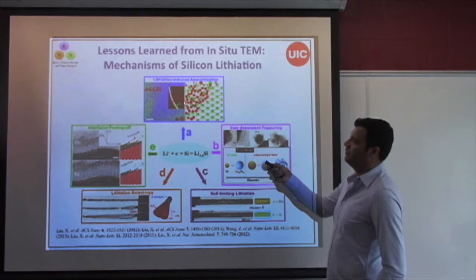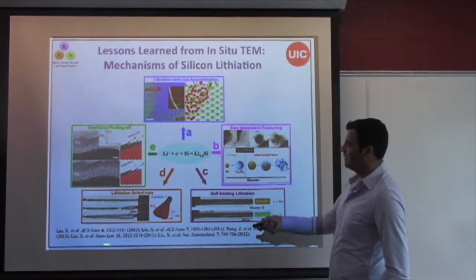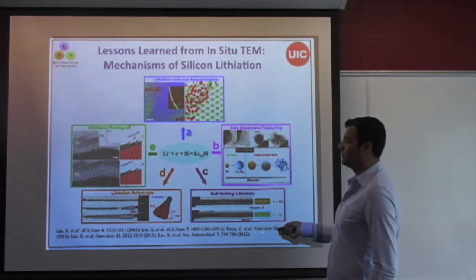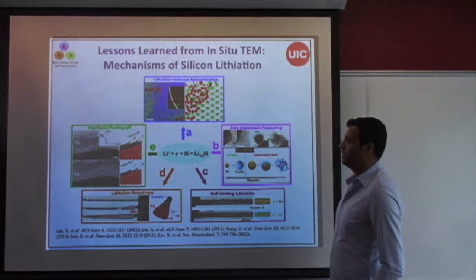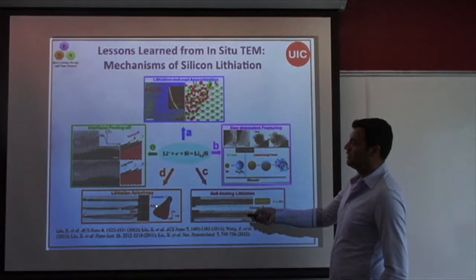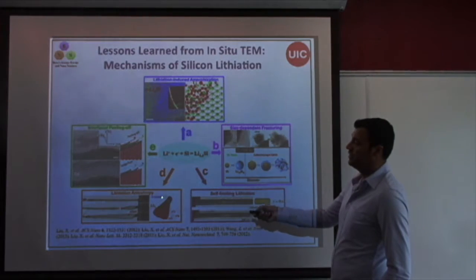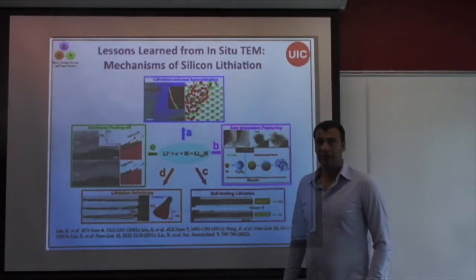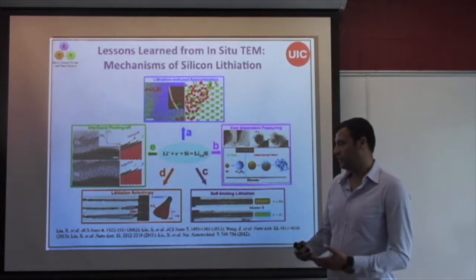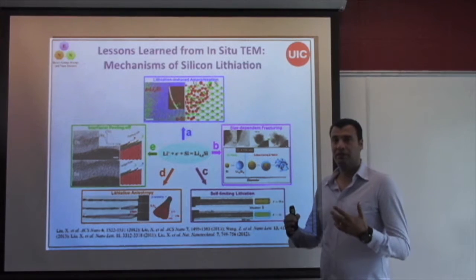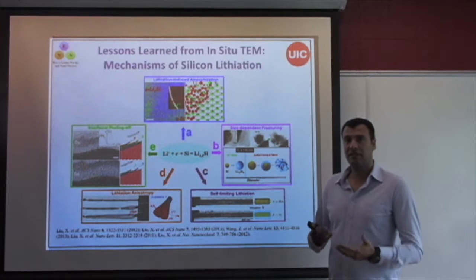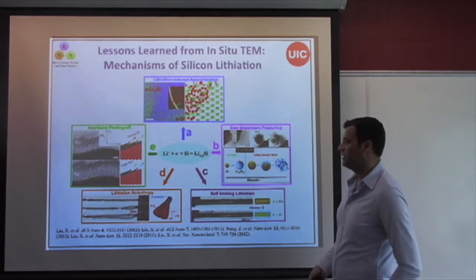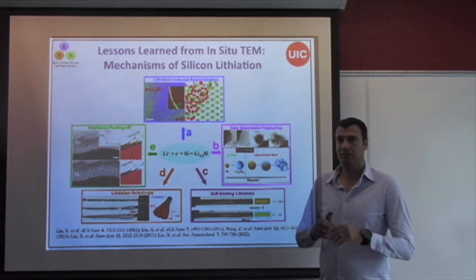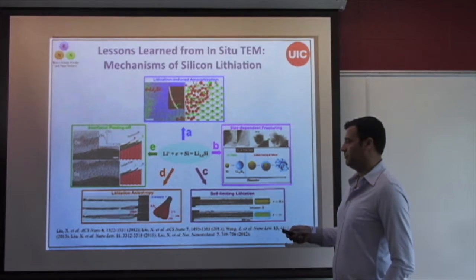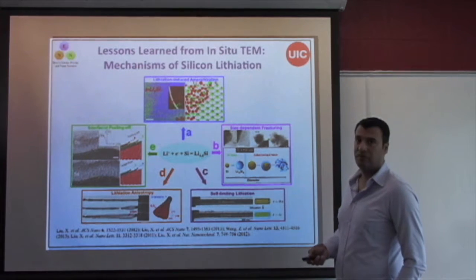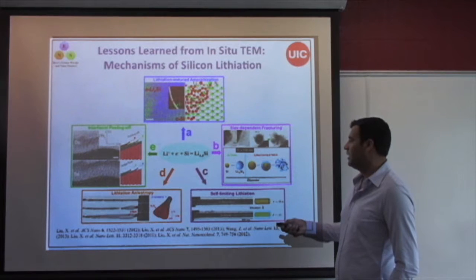This is an example of several works that have been published in the literature on silicon. People have been able to observe the lithiation anisotropy. So that was something interesting to see, that lithium prefers to alloy at certain facets of silicon rather than basically an isotropic sort of diffusion into silicon.